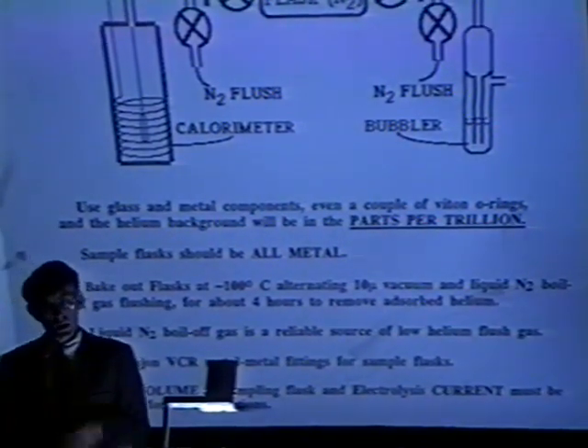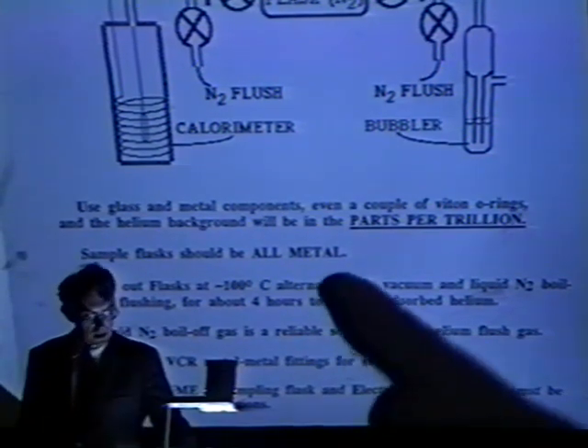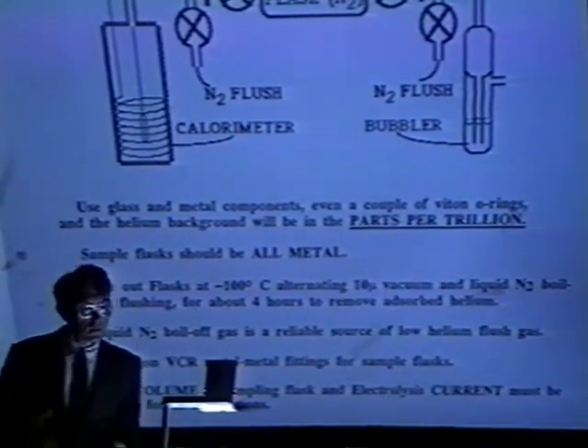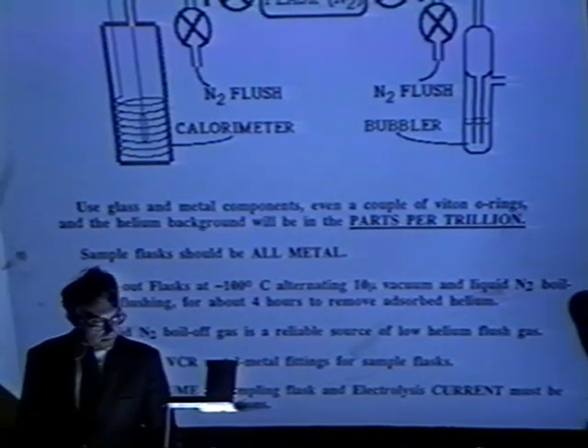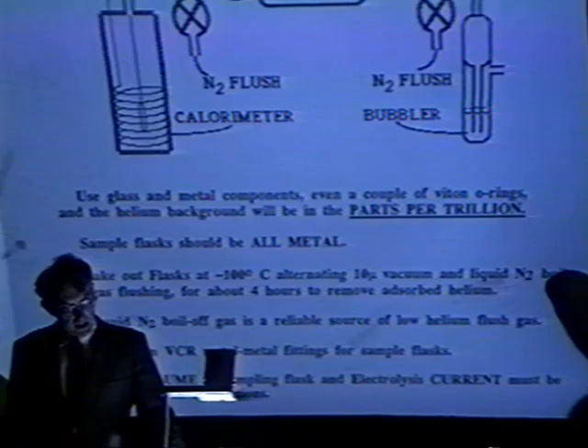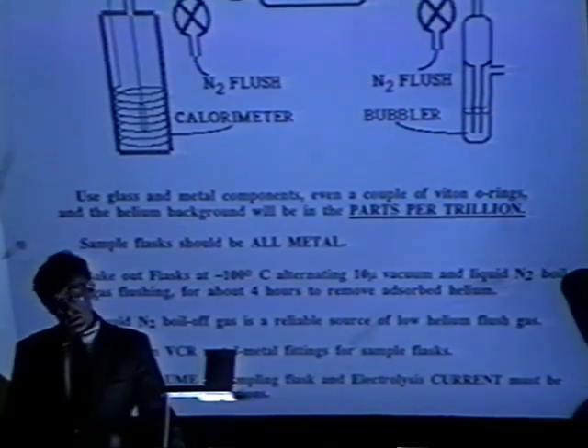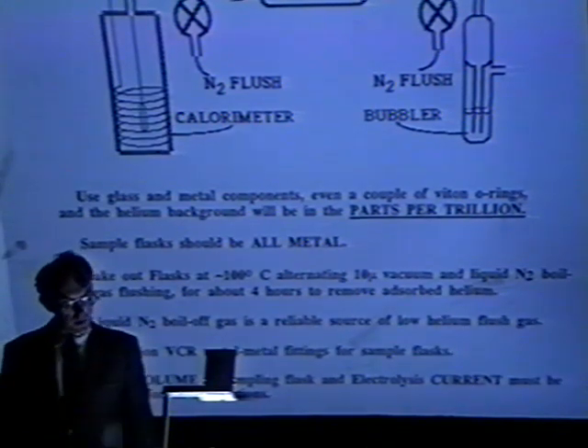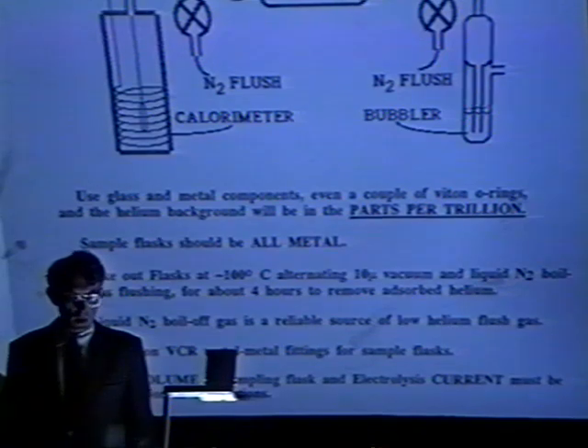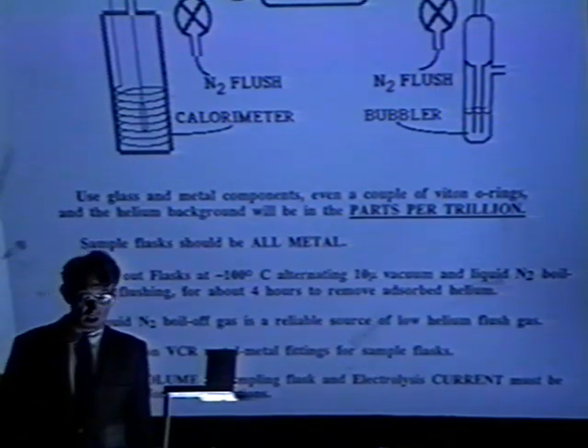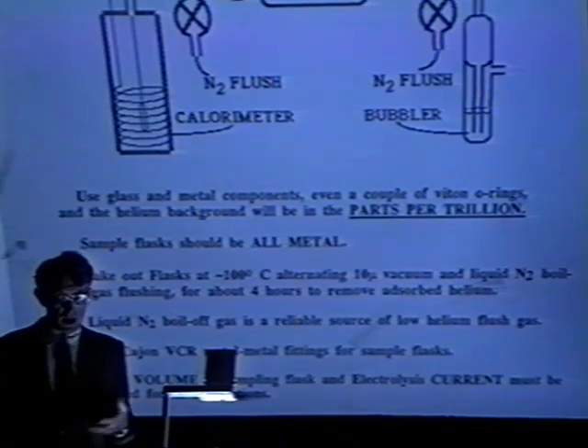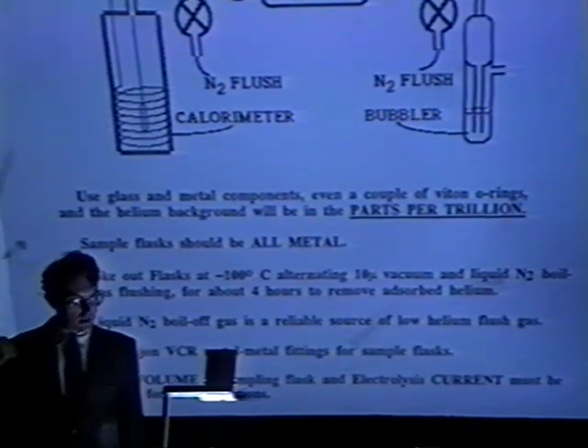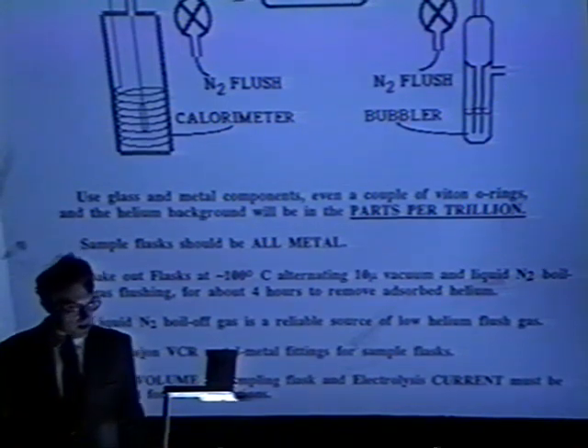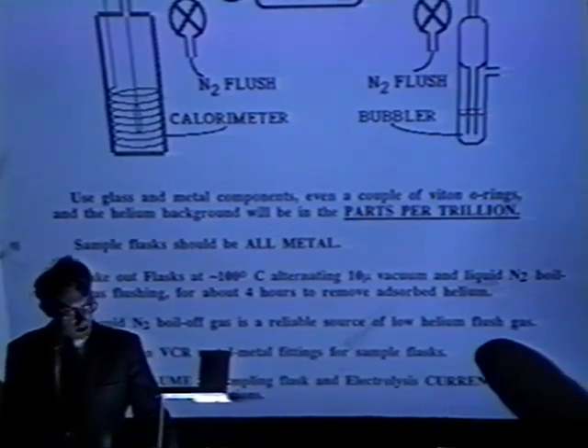Sample flasks, you have to store the samples. You're going to have them analyzed. You have to process them and so on. Sample flasks need to be all metal. Again, you don't want helium diffusing in from the air. And to clean up the flasks, you need to bake them out at about 100 degrees C under a good vacuum, say 10 microns, over a period of 4 hours, and you flush them repeatedly with liquid nitrogen boil-off gas. Liquid nitrogen is self-sparging. As the gas boils away, it flushes out the helium. It sparges it out.